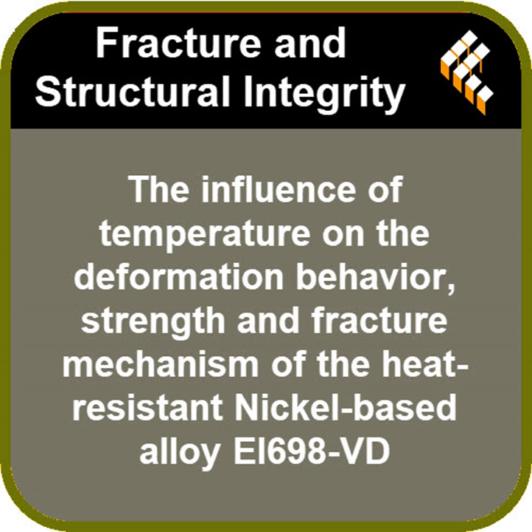Okay, so looking at the data, things seem pretty normal for a while, but then you hit 550 degrees Celsius. That's the tipping point, the critical threshold. Below that, the metal stretches. It's ductile. But once you cross 550... The plasticity just falls off a cliff. It gets brittle.